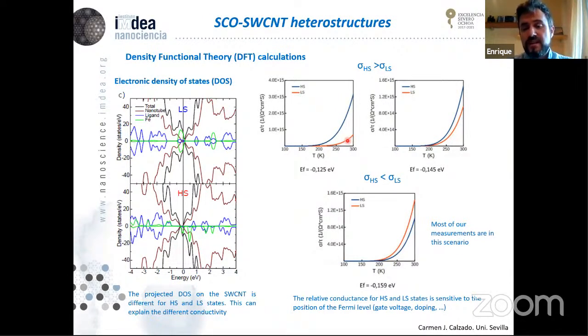We thought that this could be maybe just because our system is not ideal, so we had some defects or something, it's not really ideal, it's not like their calculations. But actually we found out that if they move the Fermi level to more negative values, you can actually reverse the situation and get into our scenario. Unfortunately, we didn't do measurements with a gate, but we can actually have this situation because we know that our carbon nanotubes are p-doped and sometimes even heavily p-doped. And the effect could be similar to moving the Fermi level.